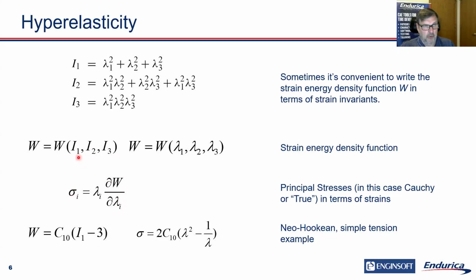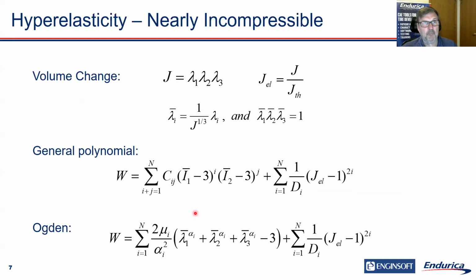The simplest form of W that we have is one that has a single coefficient for stiffness. In this case, C10. We'll see why it's 10 in a minute. And times only one term in one invariant, I1. We subtract off 3 because when there's 0 strain, lambda equals 1. So I1 equals 1 plus 1 plus 1, or 3. So we subtract off 3, so this argument goes to 0 when the strains go to 0. I can then differentiate this W with respect to the lambdas and come up with a simple stress-strain relationship in simple tension, as an example.